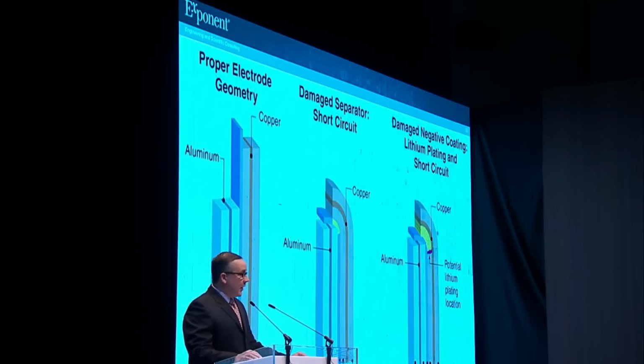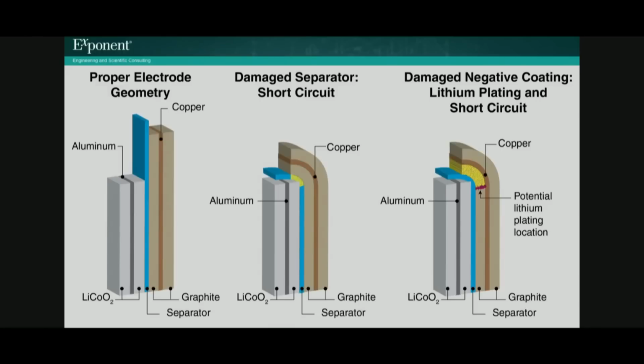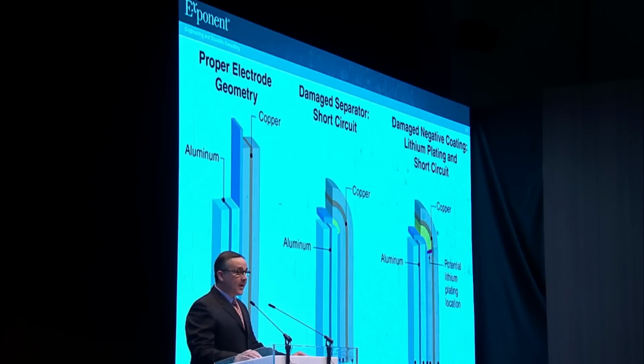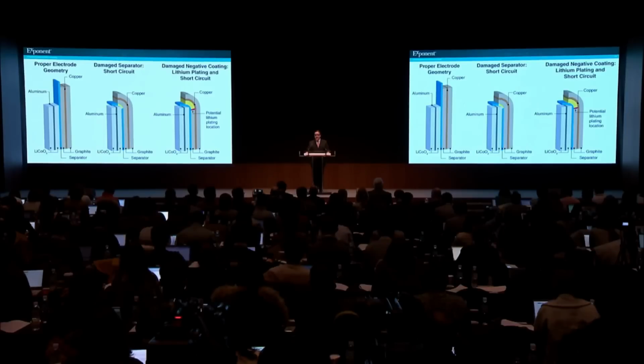The images on this slide are a graphical depiction of the positive-negative electrode arrangement at the outer wrap of the cell, and they show the two potential failure modes that could result from the electrode bending that was observed. The leftmost image depicts proper electrode geometry. The negative electrode extends past the positive electrode, the separator extends past the negative electrode, and everything is in alignment. In the center is a depiction of mechanical damage to the separator due to electrode bending that would allow contact between the positive and negative electrode, resulting in short circuit and cell heating. The rightmost image shows a scenario where electrode bending results in damage to the negative electrode coating that results in local capacity imbalance, lithium plating, short circuit, and cell heating.